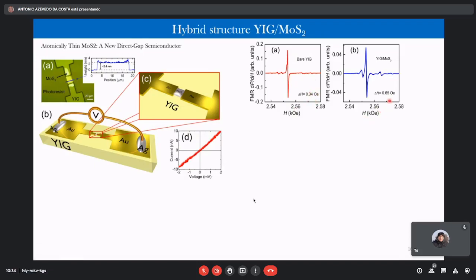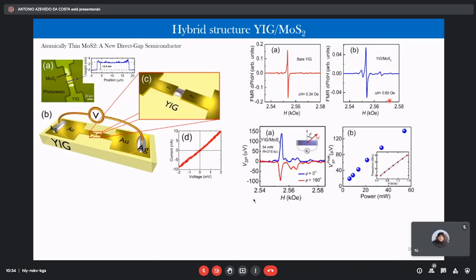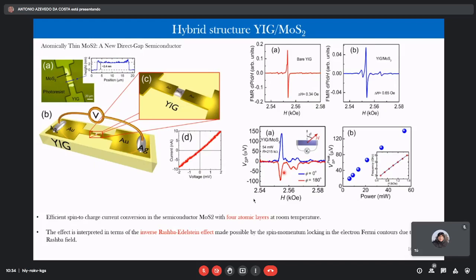It increased a little bit because in this case, when we inject the spin current into the MoS2, it loses it, so in the ferromagnetic resonance there appears an additional damping due to the spin transfer. So we measured this spin pumping signal, and what we have shown is that in spite of being a semiconductor material, a very thin one, it also converts spin into charge. This was published a few years ago.